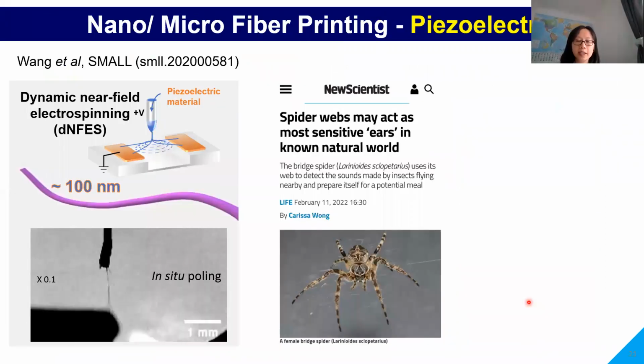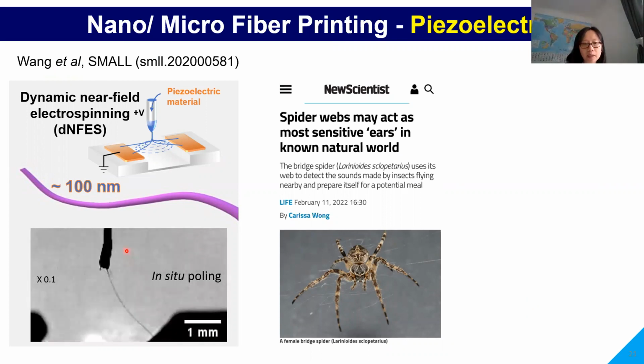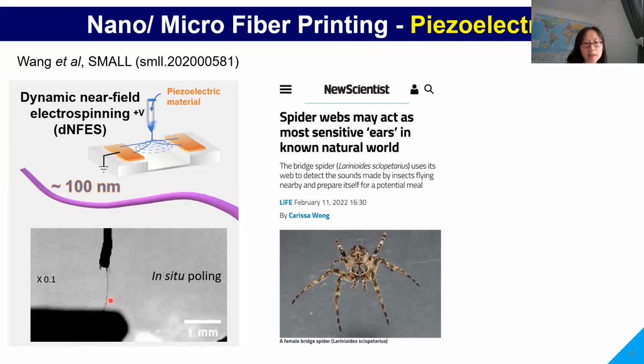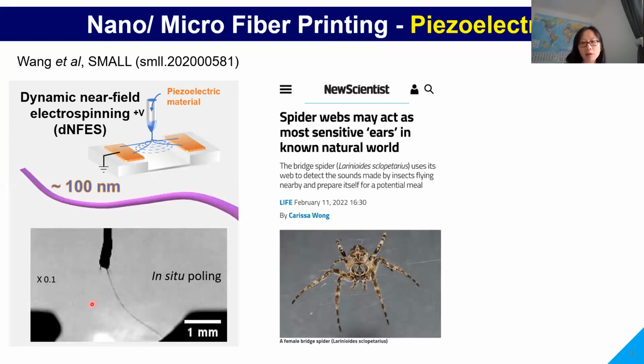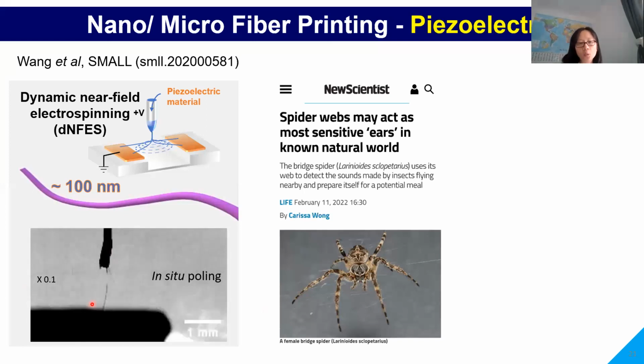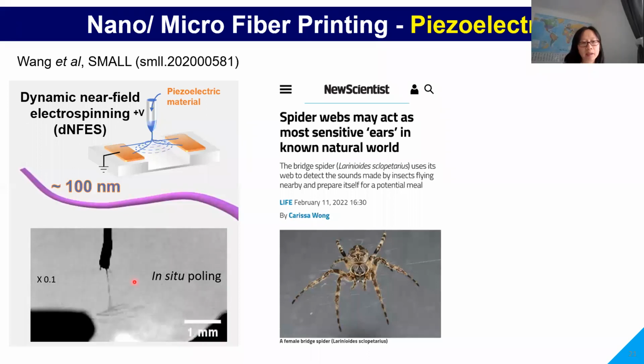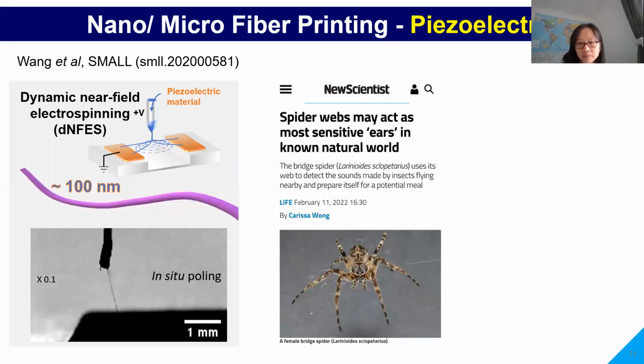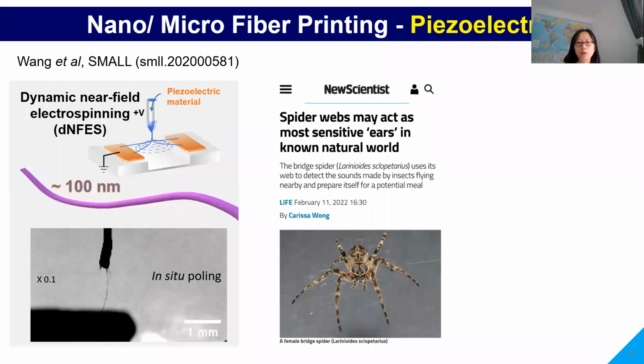The next fiber production technique developed in my lab is called dynamic near field electrospinning, or DNFES. In this process, the distortion of the electric field induces a dynamic switching between linear jetting and controlled whipping. Therefore, it can produce a suspended piezoelectric mesh bonding to two sides of the contact. And we can also in situ pole this piezoelectric material. So we use these nanofibers to create a spider-inspired non-resonant acoustic sensor.